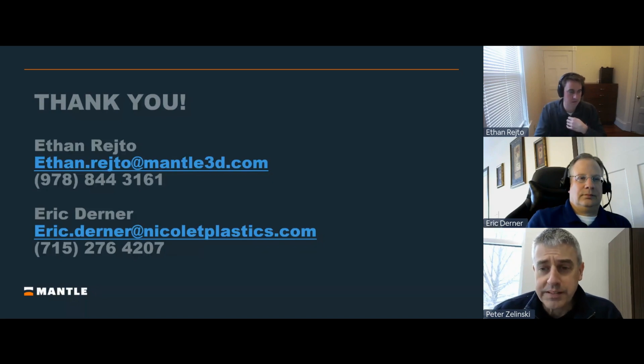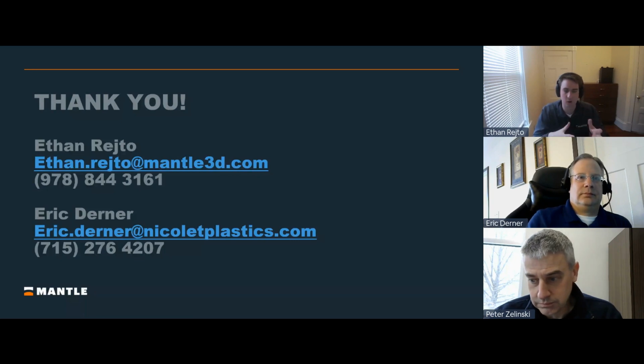You covered this, but let's hit it again since the question came in. What is the XYZ size of inserts you can print? The max size of the build on the printer, so this is the physical limit, would be 8 by 8 by 6 inches. We certainly are experimenting with some things at that size, but it becomes challenging when parts get big because as they shrink, you're moving a lot of mass. So our ideal size limit, or what we'd recommend, is more in the 5 by 5 and smaller, and then depending on the height, inches.